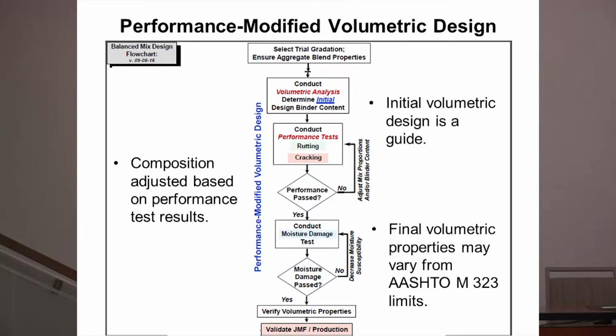With the performance modified volumetric design, the volumetric design is done at the beginning and really serves only as a guide. So what you would get is an optimum binder content. You would then conduct performance testing at multiple binder contents, let's say around that optimum. And then the composition of the mixture that you finally design is adjusted based on the results of those tests. In this case, you don't necessarily have to comply with the volumetric criteria. You simply have performance tests that you base your decision on for the binder content or the composition of the mixture. So this provides a little more flexibility in performing the design.